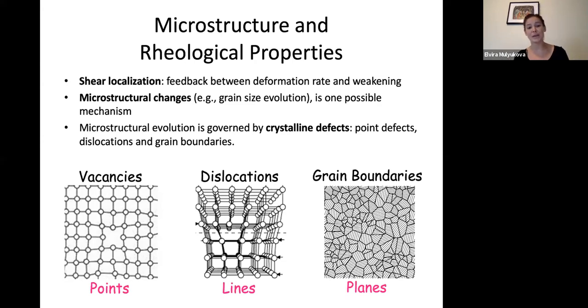And in order to have changes in the microstructural evolution, even deeper down into the physics of it, involves the formation, motion and dynamics of crystalline defects. Simply, one can think of crystalline defects, which also occur at various scales, as points, lines and planes within crystals, which are more formally known as vacancies, dislocations, or grain boundaries. These crystalline defects are not independent, they interact with each other. And some of these interactions will then, on a larger scale, manifest themselves as the overall strength or rheology of the rock. So we're gonna look at how these crystalline defects evolve and what they mean for the rheology.